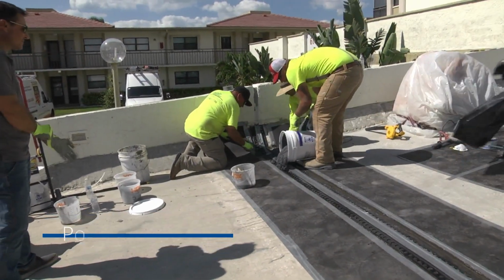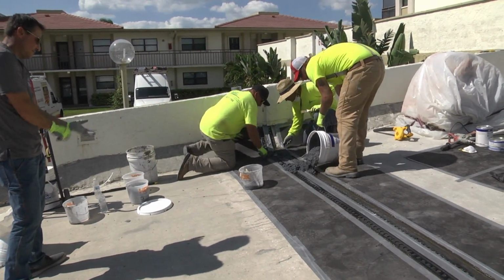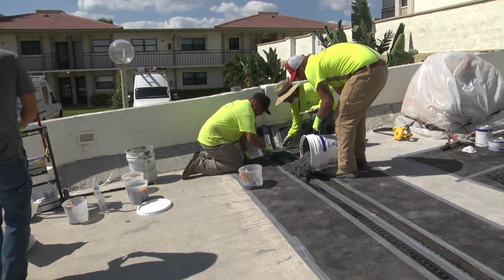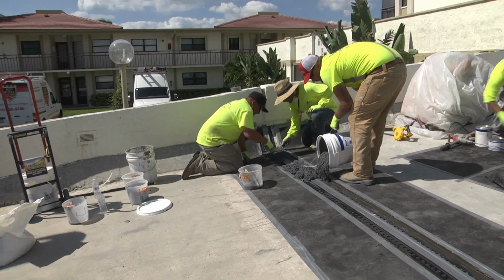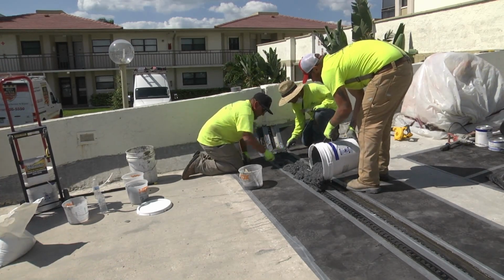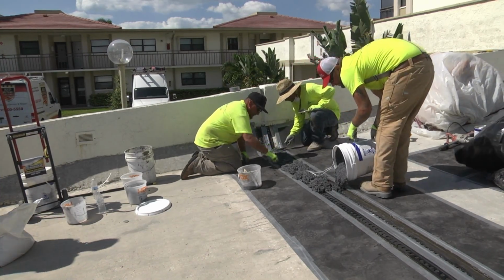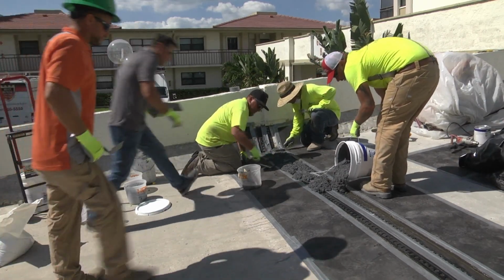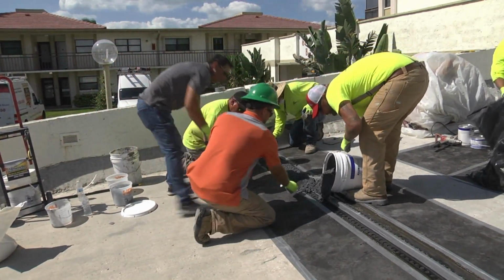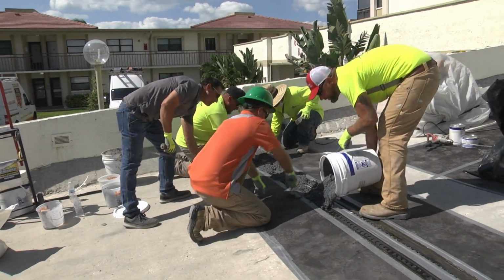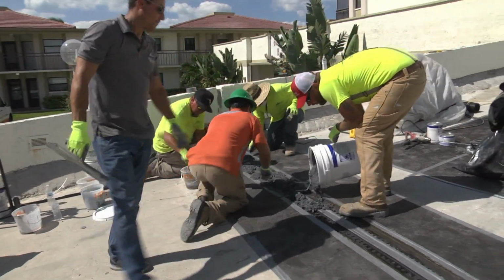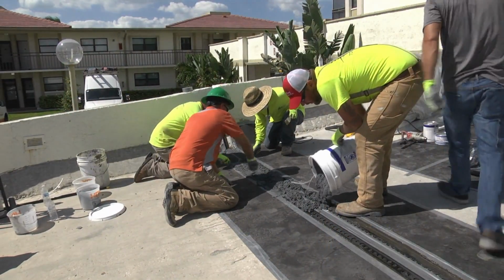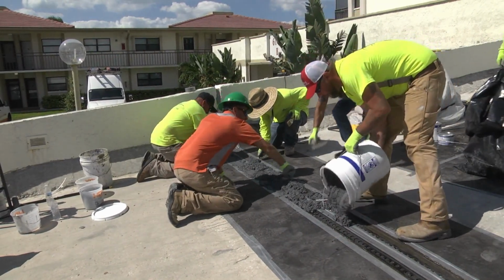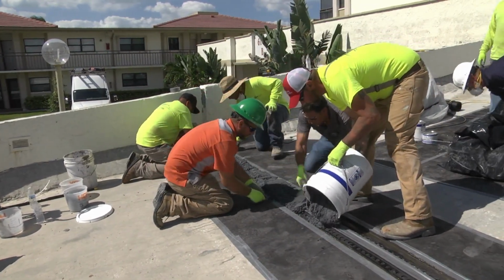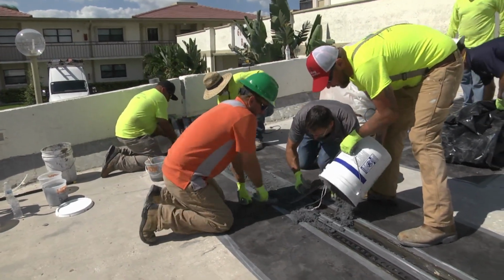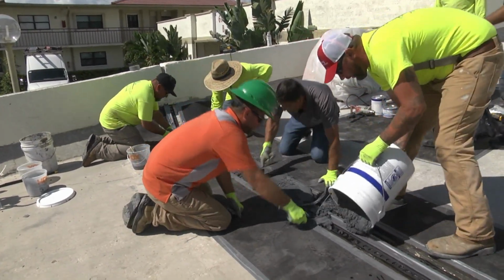What we want to try to do, as we're emptying the contents out of the bucket, is make sure that we're moving and walking down the joint line, pushing and spreading the material as we go down. You can see that it is a thicker consistency with the non-flow additive added to it, and really that's what we want for this type of slope condition on this deck. Otherwise we'd have to go back and rework it and rework it, because it's a self-leveling based material. But the key is to push the material down and make sure we get all the material out of the bucket.